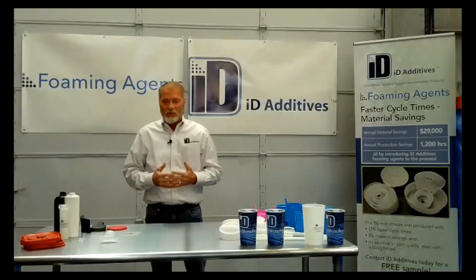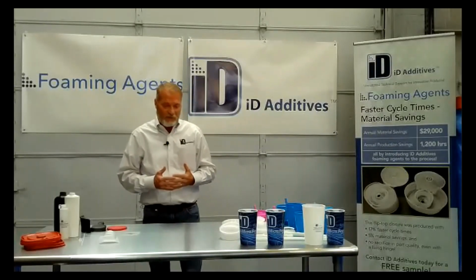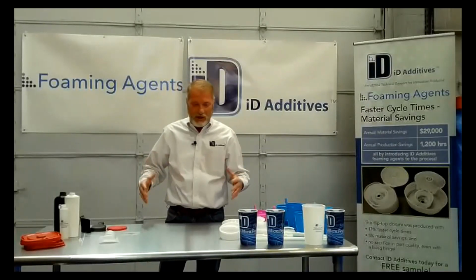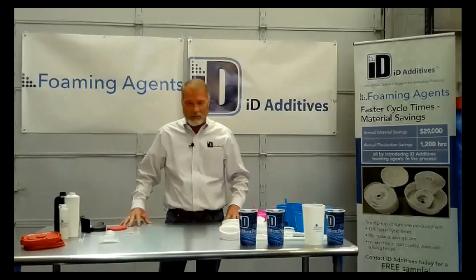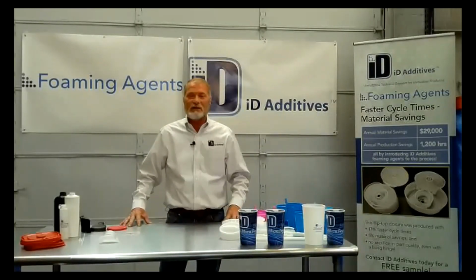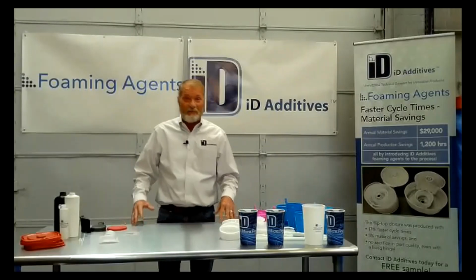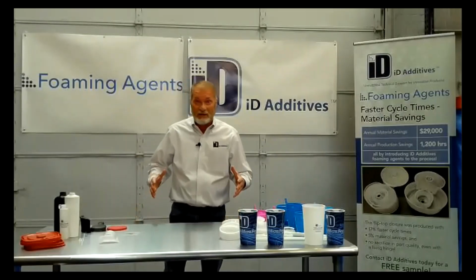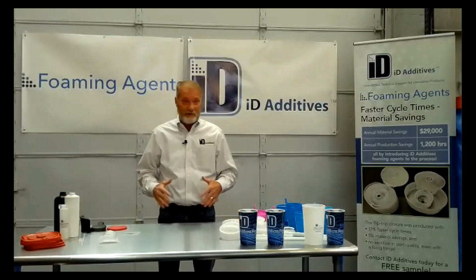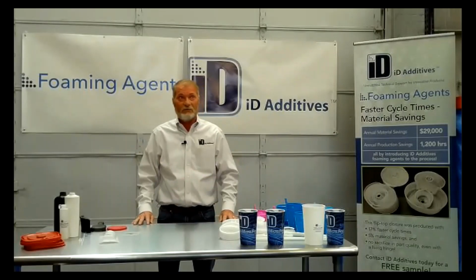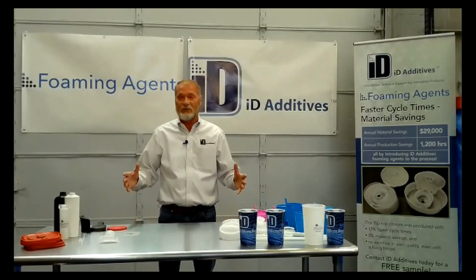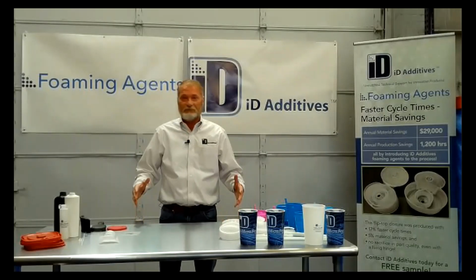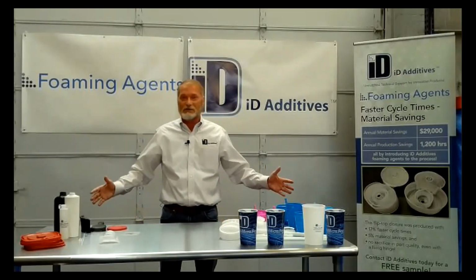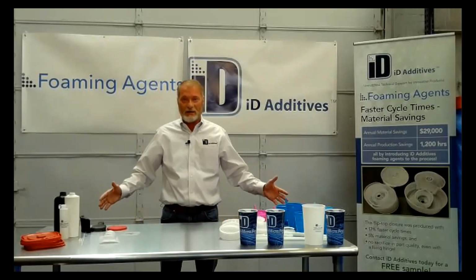So you want to take advantage of foam. And what I typically, when I do a trial, I'll go in and talk to people, I emphasize that viscosity change. That viscosity change is huge. You can drop temperatures. I've gone from 20 to over 100 degrees off of barrel temperatures just by adding a chemical foaming agent.